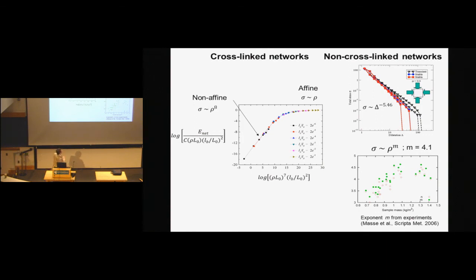But the exponent of this power law, that is the scaling of stress with density, this exponent m is about 4, while the other two exponents were 1 and 8 respectively. So one good news, one bad news. The good news is that both of them behave as power laws. The bad news is the exponents are not the same. Okay? Why is that? We don't know.